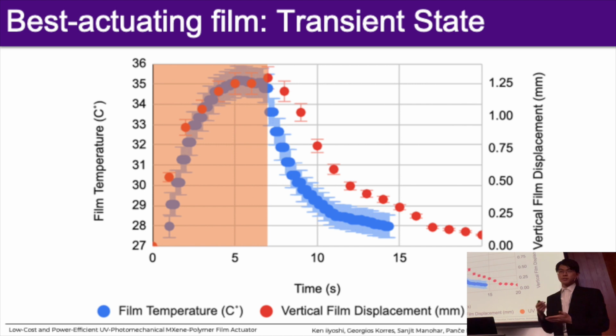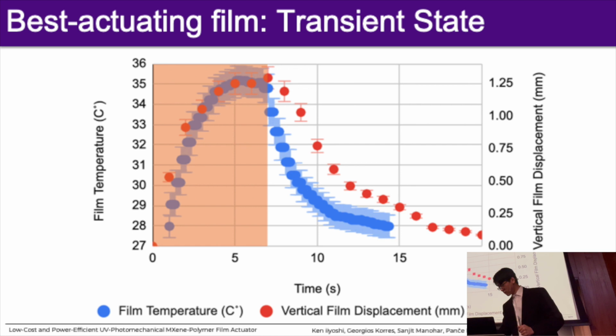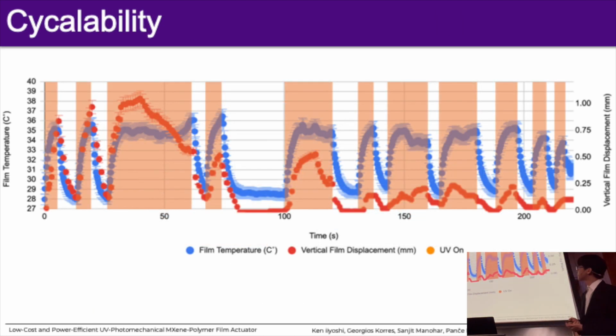Now, because this presentation is about characterization, we wanted to test mainly the transient response, the cyclability, and the steady state response. First, for the transient, for the orange shaded part, which is where the UV flashlight is turned on, we can see that as the temperature of the film increases, the vertical film displacement goes along with it. Same with the off stage. Once the temperature goes down, there's probably a bit of hysteresis-based lag, but the film also goes down. And we managed to do 11 cycles of actuation, as you see on this figure.